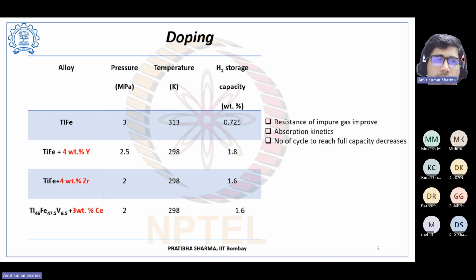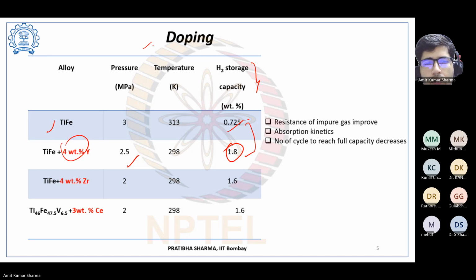And by doping also we can change the properties. This is the alloy TiFe, and if you do doping with 4 weight% of yttrium, you can see the change in properties. The pressure decreased from 3 to 2.5. The capacity increased to 1.8 weight% from 0.725, a huge jump. Then with 4 weight% of zirconium, the pressure further decreased to 2 megapascal, temperature 298, capacity 1.6. So in this alloy, this is doping, and this is the effect.